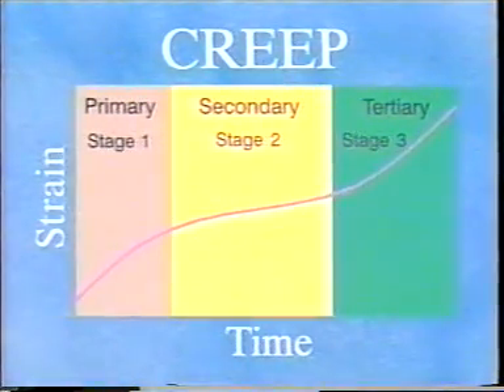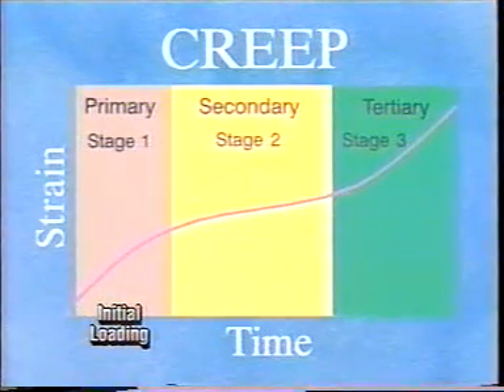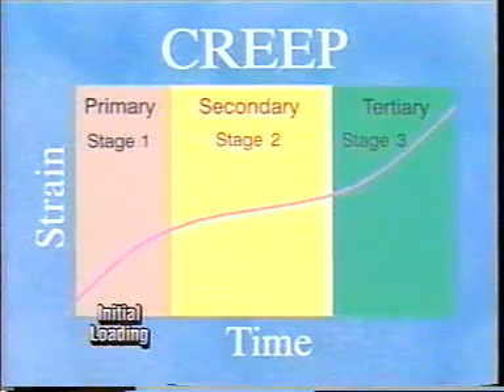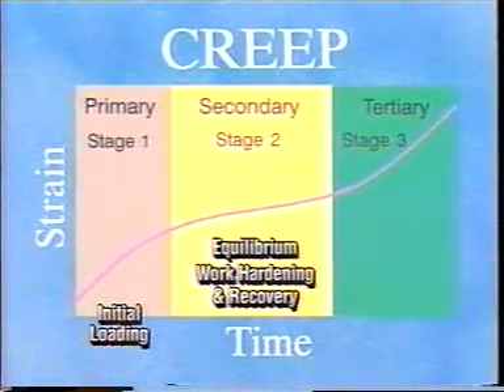The first stage of primary creep can be explained as an adjustment within the metal which occurs in the first few moments after the initial loading. Under this initial loading, the crystallographic imperfections begin to undergo realignment and the creep rate decreases. This leads to secondary creep. Second stage creep is an equilibrium condition between the mechanisms of work hardening and recovery. It is characterized by a constant but usually a relatively low creep rate. This secondary steady state creep is essentially a transition between primary and tertiary creep, even though it usually takes most of the time during a creep test.